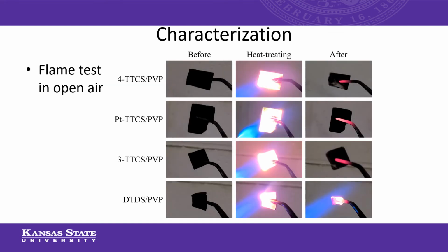We have exposed our fiber mats to the acetylene flame torch for 20 seconds, and platinum TTCS sample showed the best overall thermal performance, where it didn't shrink or oxidize on the surface. So 4 TTCS and 3 TTCS showed a slight burn at the surface. However, DTDS showed a complete shrinkage and then burn after the flame test.